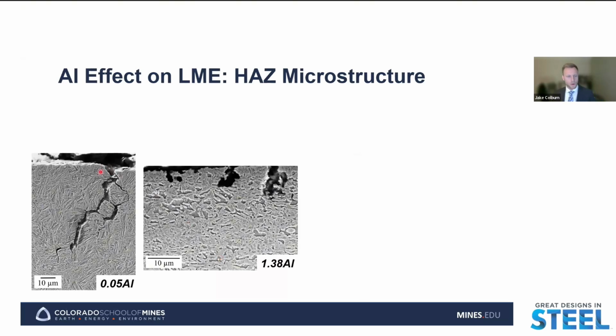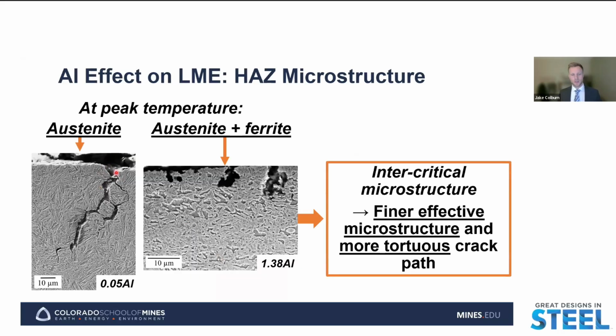But even more than just potentially affecting the zinc enrichment and penetration behavior, changing whether we have an intercritical or supercritical microstructure at these LME susceptible regions can potentially affect the crack propagation path, to where again, at peak temperatures, we expect the supercritical heat affected zone to be single-phase austenite, so we can get zinc enrichment and penetration along those prior austenite grain boundaries more easily than in the intercritical microstructure, where we have austenite plus ferrite at the peak temperatures. And we can even see here with these small cracks formed that are roughly 10 microns or less, to where there's potentially some crack arresting here due to not having sufficient zinc penetration into the substrate.